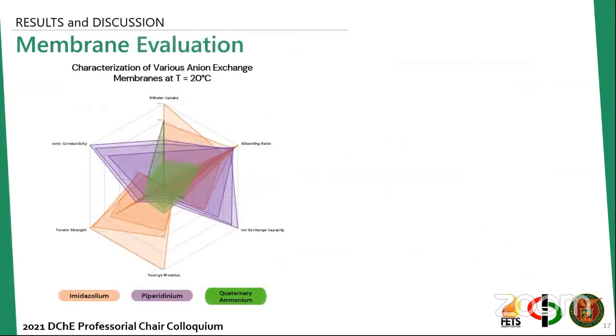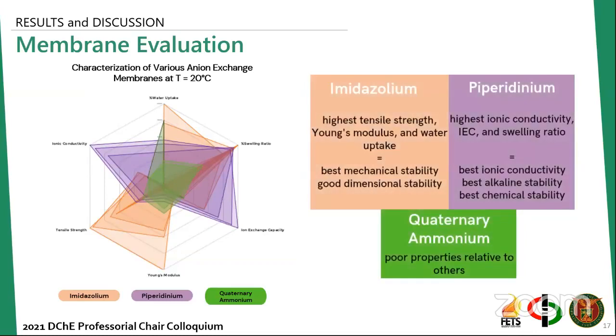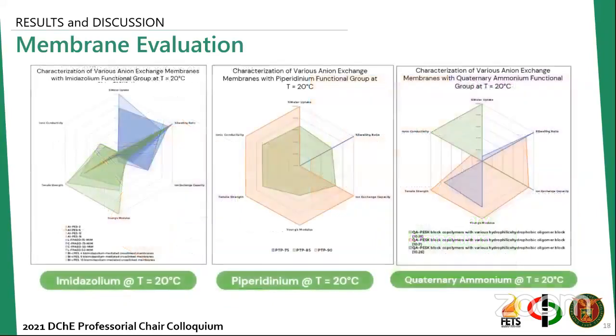Okay, for the results and discussion, we look at the characterization of the various anion exchange membranes. Based on the 3 functional groups and this radar plot, we can see that the imidazolium has the best mechanical stability and good dimensional stability. The piperidinium has the best ionic conductivity, best alkaline stability, and best chemical stability. And lastly, quaternary ammonium, compared to the first 2 functional groups, has poor properties. Then radar plots of the specific membranes under each functional group are shown, and they show the individual performance of each membrane relative to its functional group classification.